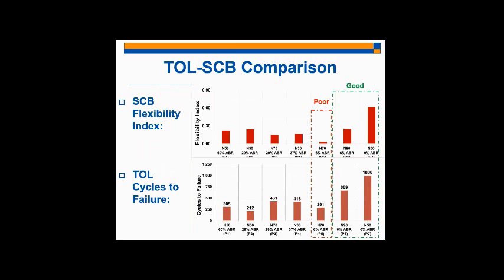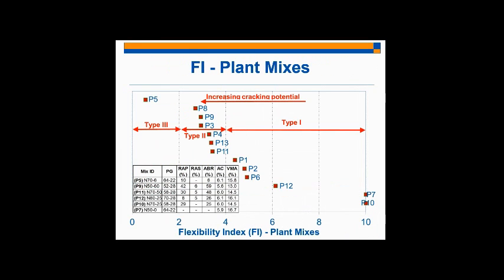So you're referring to these, right? Yeah. These thresholds, as I mentioned, are preliminary, and they need to be fine-tuned as we increase the database of field performance. Where they're coming from now is basically engineering intuition, coupled with the mix design properties of the different mixtures that are being tested. You would expect a mixture with lots of recycled content, with lots of RAS, to be a poorer performer in the field. So these are very preliminary thresholds, very open to refinement in the future.